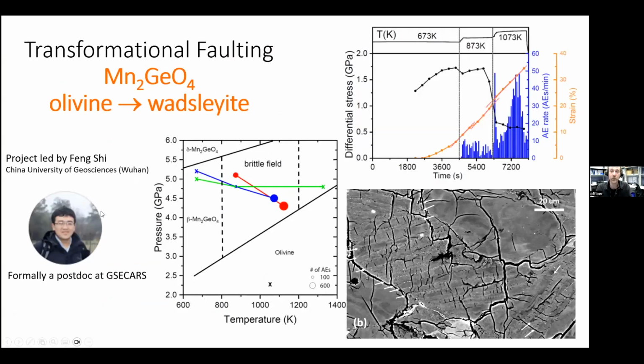This is just saying we also perform the same type of analysis. Instead of using Mg2GeO4, we use Mn2GeO4, which transforms from olivine to Wadsleyite. This was led by a former postdoc at GSECARS named Feng Shi, who's now at the China University of Geosciences in Wuhan. And basically you get the same thing. You have a narrow temperature window in the high pressure stability field where fracture occurs. It doesn't occur in the olivine stability field.